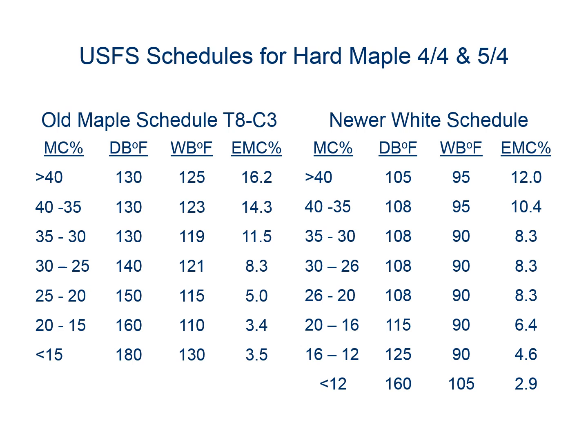And on the right, the EMC is the equilibrium moisture content, and that is how dry the air is that we're trying to get our wood to. So you see on the left side we start at 16 but with 130 degrees, and on the right we're at 12% moisture content and we start off at 105. So the one on the right is a milder schedule.